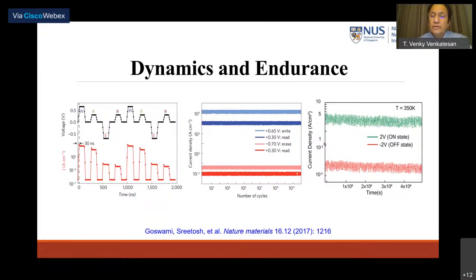If you now put these states in a high temperature of 80 degrees centigrade, and you leave them in an on state or off state, then they are rock steady over a period of 3 months, basically. This is from here to here, a 3-month period, and there's no change at all in the device characteristic.